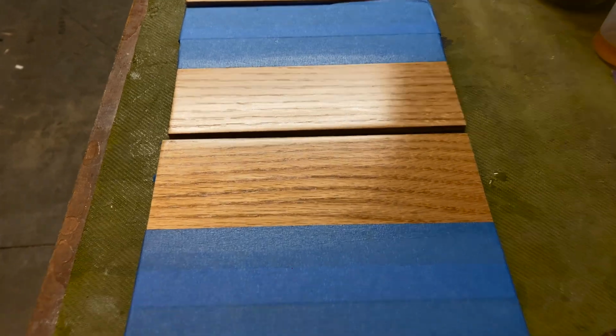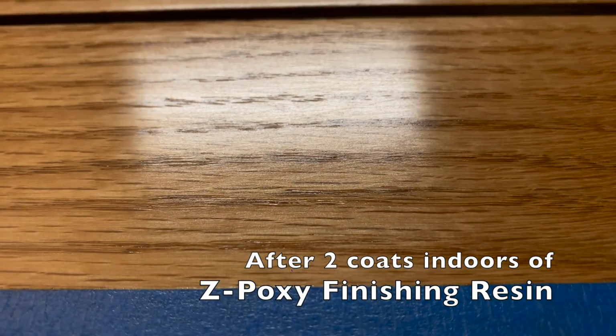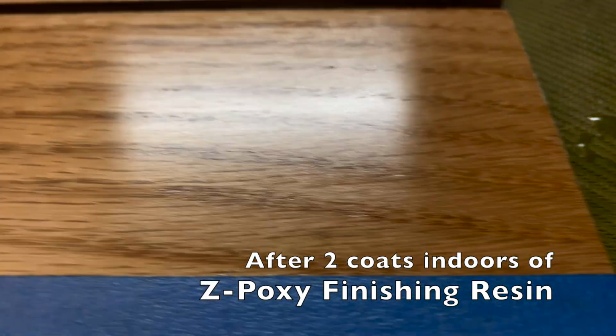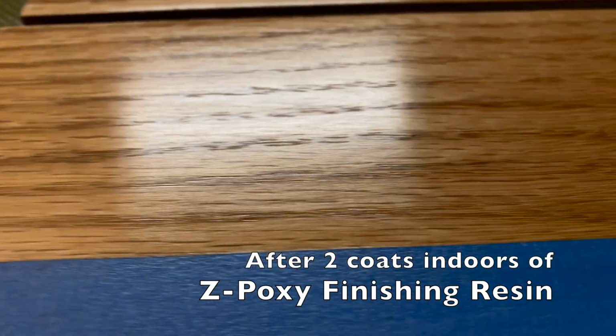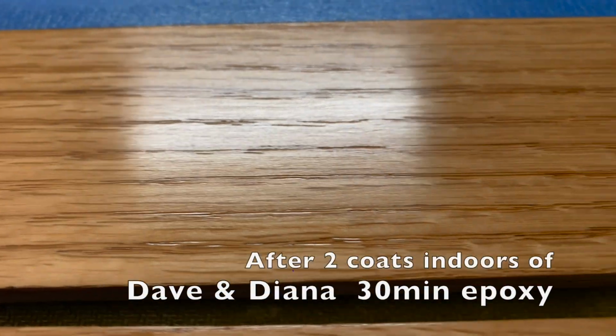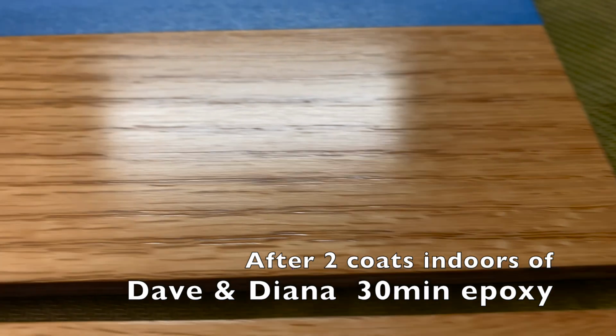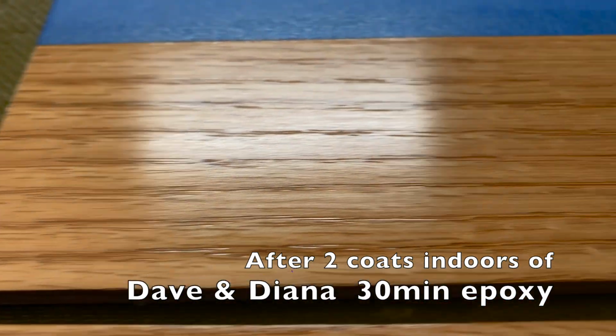The Z-poxy and the Dave and Diana still showed grain, but you can also tell that the areas that were shellacked on the right sides of the boards were filled in just a little bit better. The grain showing here really didn't surprise me because of how thin of a coat I was able to get on these boards in the warm environment.